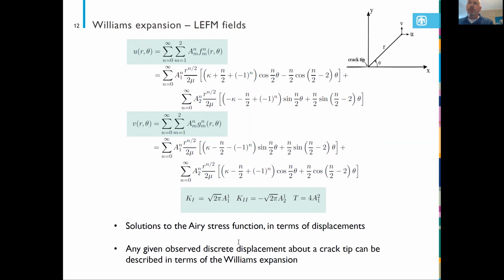These are linear elastic fracture mechanics fields. Linear elastic fracture mechanics originates from continuum assumptions about materials. But ultimately, these displacement fields describe the Cartesian displacements U and V relative to your sample in X and Y. So you have a crack tip centered at the origin here, and you have crack faces that propagate off into the negative X direction here. So the X axis is along the central crack face plane. Now these functions describe the displacement at a given radius and an angle relative to that crack face plane.